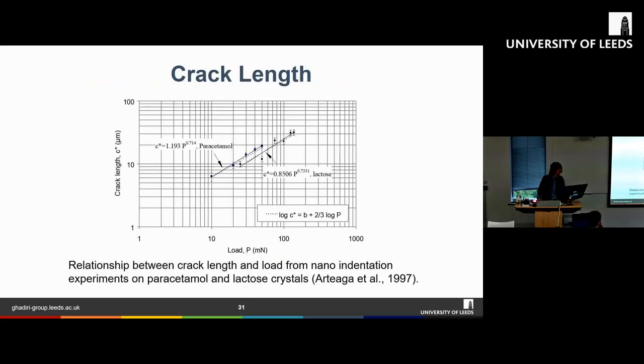Okay, if you now plot the crack length versus the load, this is the work done by Arteaga et al. in 1997, on a logarithmic scale, we can see that we get a very nice linear relationship, and the slope of this line actually gives us a measure of the fracture toughness of the material.